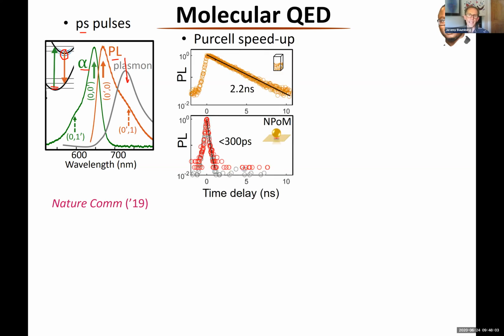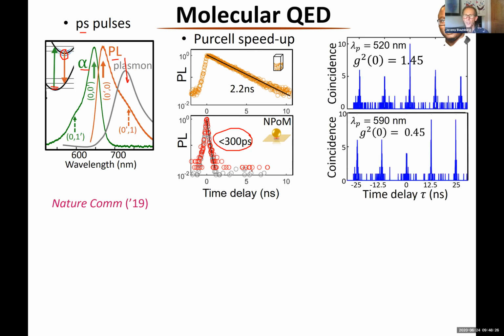So if you look at the luminescence of this dye molecule in solution, then you'll find it's a couple of nanoseconds just as you expect. But inside the gap here, it's much faster than we can measure. There is no way, in fact, to measure the correlations of photons because the emission is on the order of the splitting, which I was showing you before, on the order of 50 to 100 femtoseconds. We don't have single photon detectors which work that fast. So that's why we use picosecond pulses here, so we can look at the correlation.